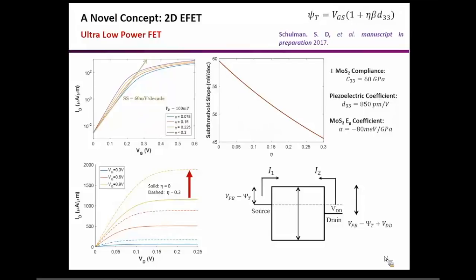One is this strain engineering parameter, which comes from the structural part of the device. This beta part actually comes from the 2D material. If you have a 2D material which has a much larger change in the band gap for a given applied pressure, I will prefer that 2D material, right? Because that will give me more band movement. And at the same time, for the piezoelectric coefficient, you want to select a piezoelectric material which expands more for an applied gate bias. So all this material engineering can take place, and we can even go to a smaller subthreshold slope depending upon the material combination we choose.